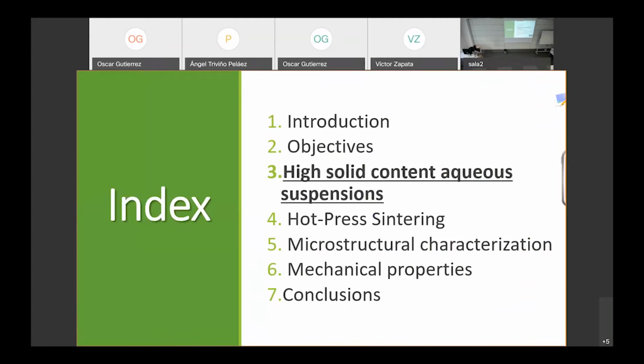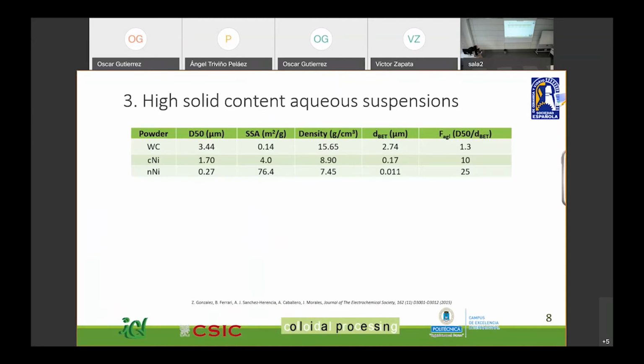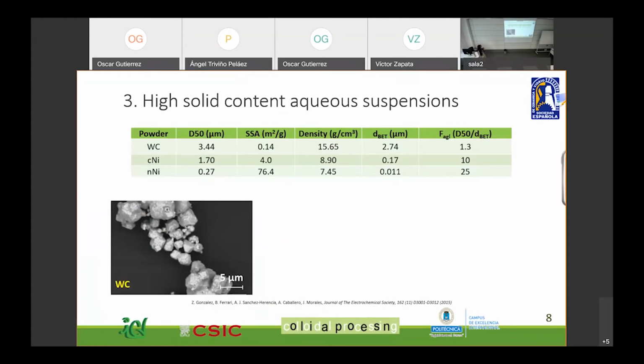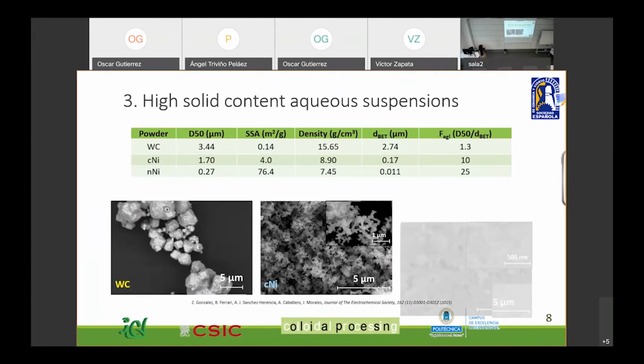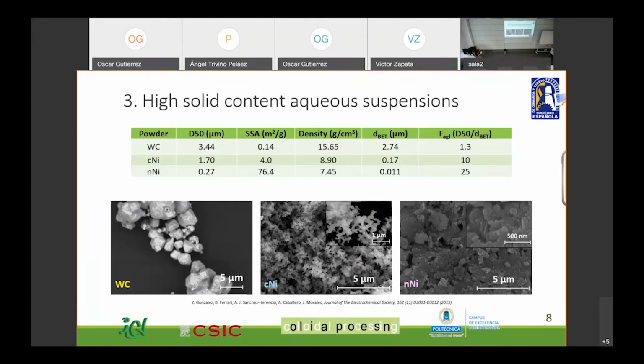So the first thing we are going to talk about is the preparation of the high solid content suspensions. First thing to mention, the powders we're going to use all over this work. As you can appreciate here in the micrograph, we have a micronic tungsten carbide powder, which actually has a not very high specific surface. And also we use 2 different types of nickel. The first one is a commercial nickel, that's why we call it C nickel. And the second one is a nanometric nickel we synthesized in our lab. Here I attached the reference.